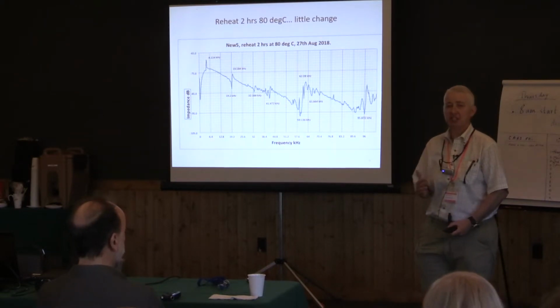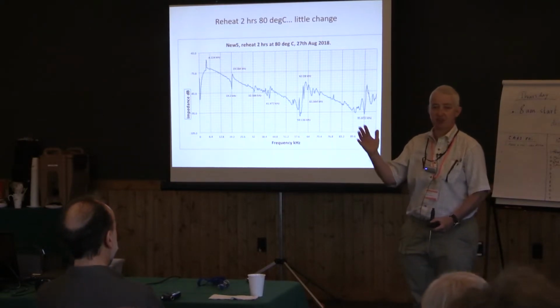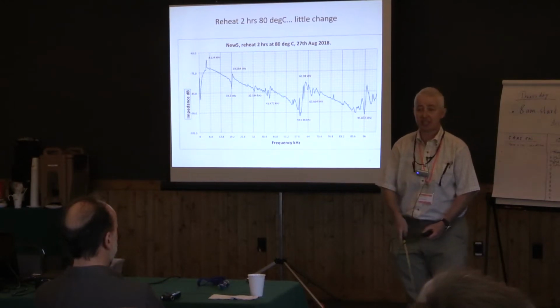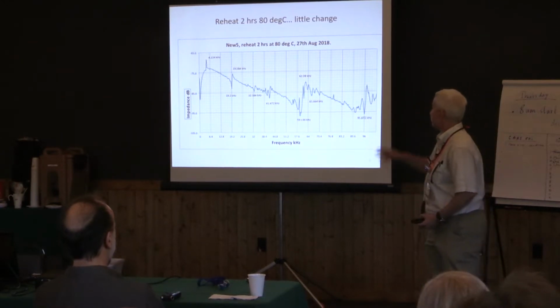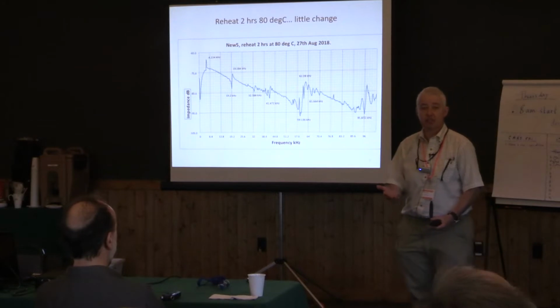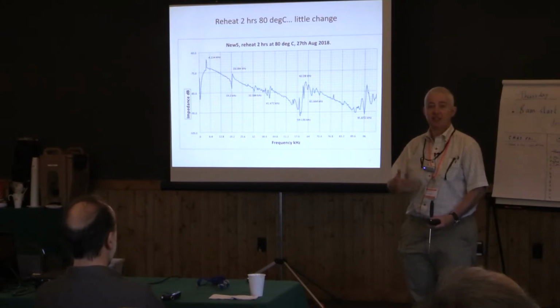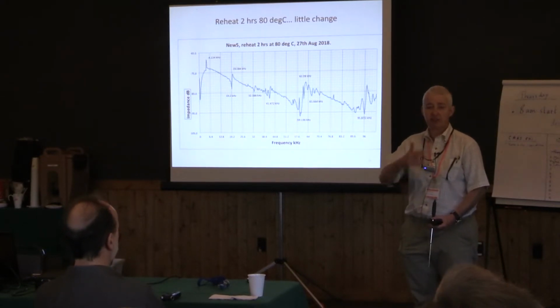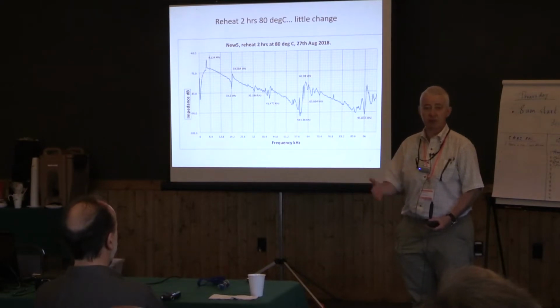Right, not necessarily going straight to the manufacturer's recommended setting. Maybe we have to do a little bit of testing and decide, maybe we start at 70, then go up to 80 degrees C, and then 90 degrees, and then the recommended 100 degrees C, and we figure out which one of those is the best for what we want to do.